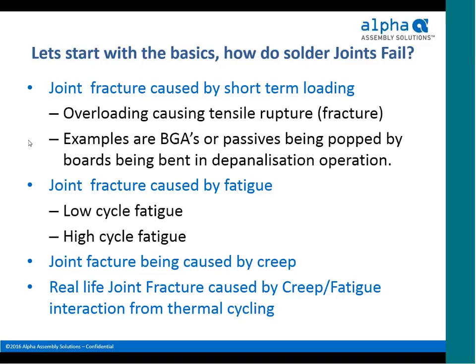This next category would be where we have either low cycle or high cycle fatigue, whether it be failure at a low number of cycles, or end-of-life type failures after a high number of cycles. There's also joint fracture that can be caused by creep. So under the conditioning of static mechanical stress, you can get failure over time.